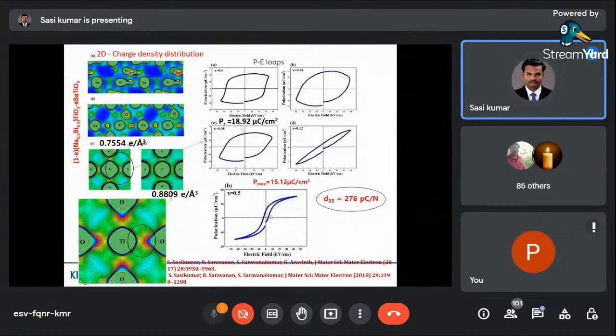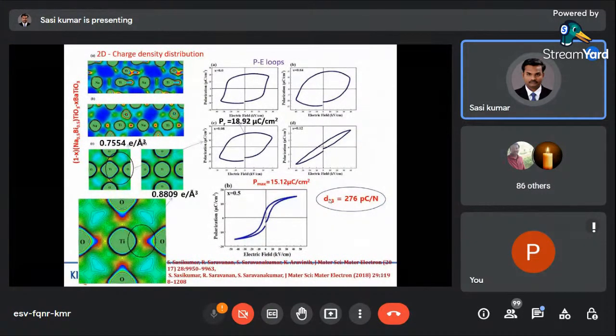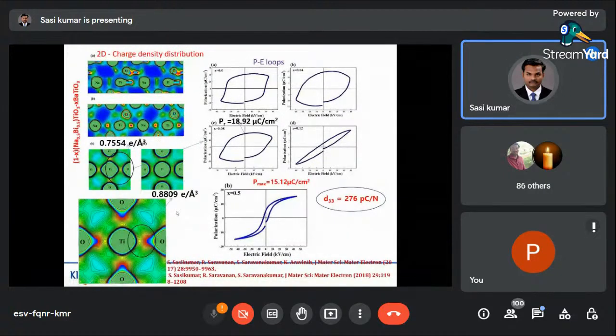And then another composition, barium zirconium titanate and barium calcium titanate modified samples, x equal to 0.5 possesses higher ferroelectric property, P max equal to 15.12 microcoulomb per centimeter squared, and it possesses higher d33 value, 276 picocoulomb per Newton. So this is also one of the reasons, correlated with the bonding between the titanium and the oxygen atom having higher mid-bond electron density values. This is also considered as covalency.